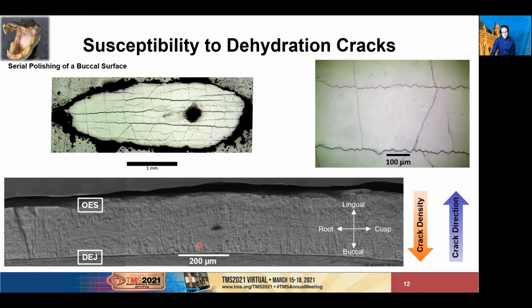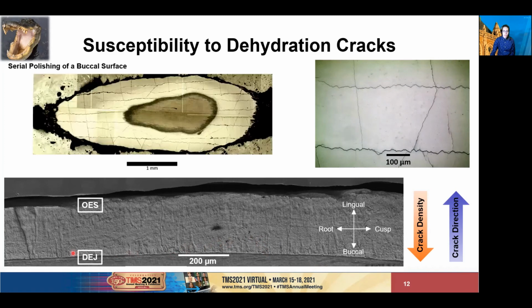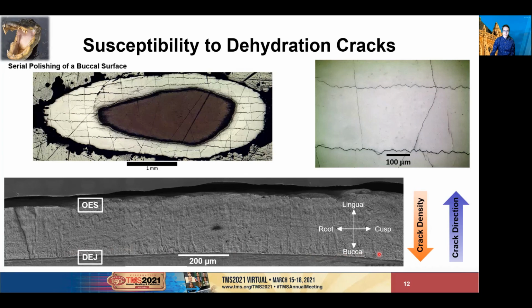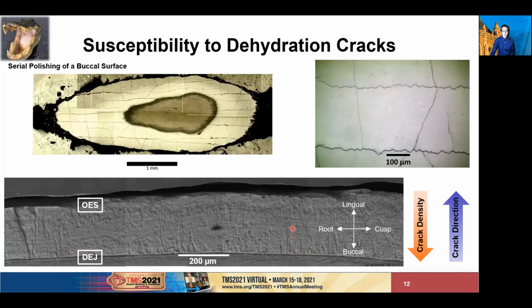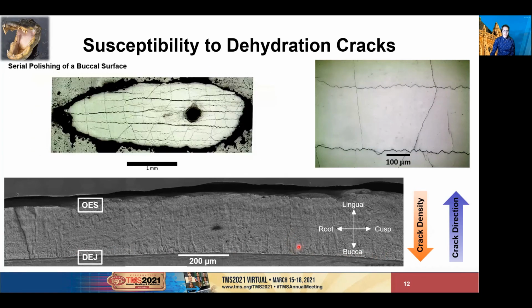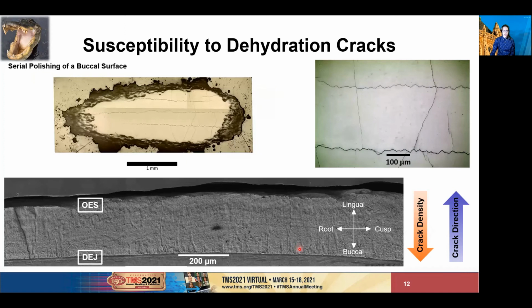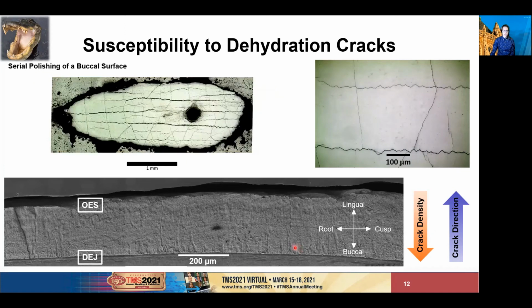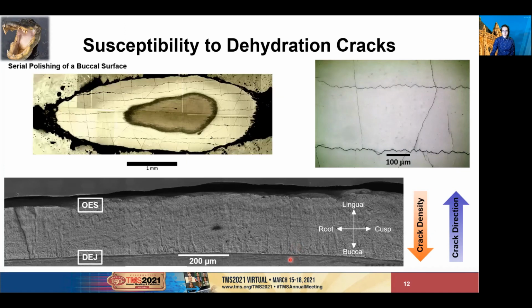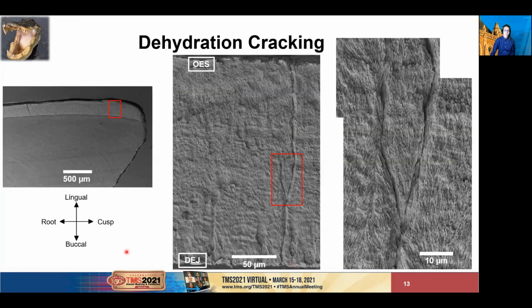Numerous smaller ones, you can also see those closer to the DEJ. The increased frequency of cracks combined with the direction of the crack, you'll see that on the next slide, tells us that the cause of these cracks is the shrinkage of the dentin tissue, which experiences much larger dimensional changes with hydration than enamel does.